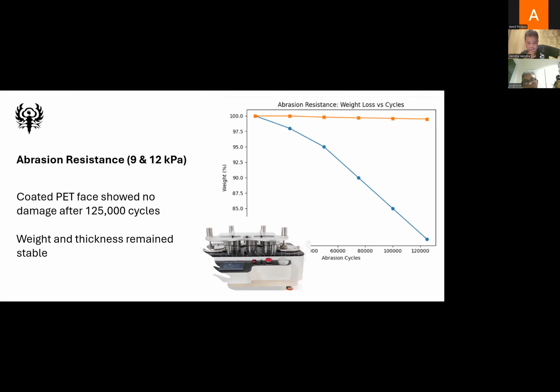Based on the abrasion resistance test, they conducted two tests at 9 and 12 kilopascal. From the diagram we can see that even after 125,000 cycles, the coated polyester face did not suffer any damage, and the measurements of weight and thickness also remained stable. The orange line is the coated fabric, and the blue line is the uncoated fabric, so we can see the significant difference made by the coating process.